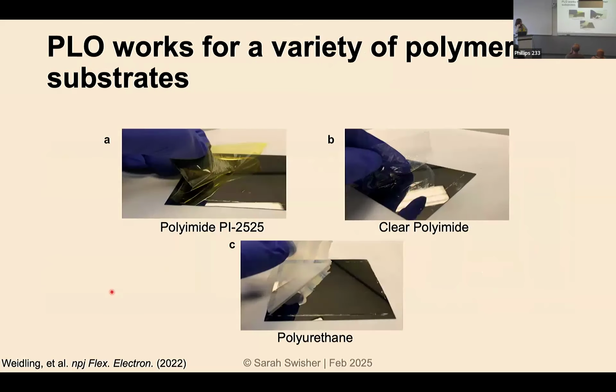It's also nice because it works for a variety of polymers. So I mentioned that we have that light absorber layer, and so we're not relying on the polymer to absorb this photonic pulse that's coming from the back. It all gets absorbed in the metal. And so what that does is it decouples the light source from the polymer and its absorption profile. So all we need is the heat, right? And so we can do clear polyimide, we can do polyurethane, we can do different types of polyimide that have different properties. And they all work because it's sort of agnostic to the polymer that you're using. You're just heating because the metal itself is absorbing.